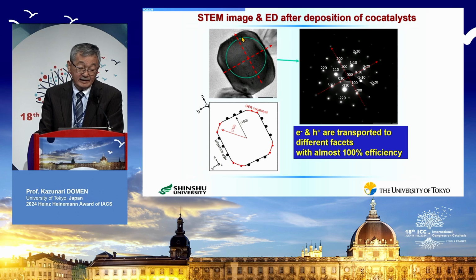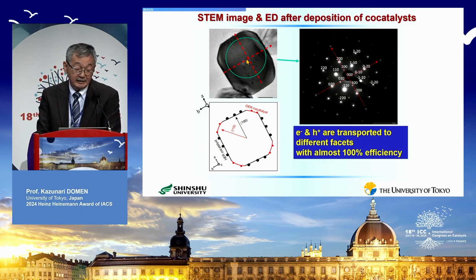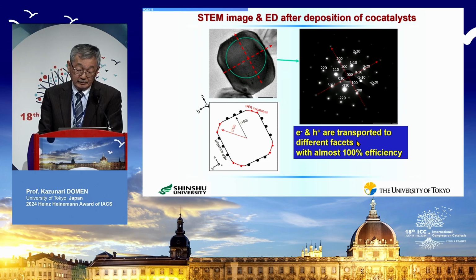In addition to that, there are many different facets a little bit curved like these ones. In this case, we are not able to identify them. But for simplicity here, let me say that this is 110 facet. And on this 110 facet, we observed only the oxygen evolution co-catalyst. That is the cobalt hydroxide. That means that from the very beginning stage, photoexcited electrons and holes are transported to different facets with almost 100% efficiency. Then the question is, what is the driving force?